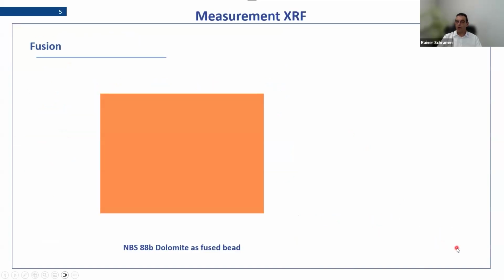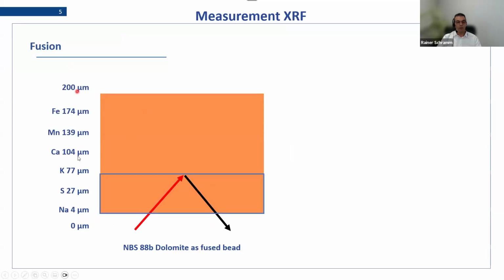But let's think about, we have a glass bead. And the glass bead was made from a dolomite, with a dilution ratio 1 to 8. So 1 part sample, 8 parts flux. And then the main question is, where is our information coming from in the bead? And for this, I just mention here the penetration depth for different elements. And you see that with increasing atomic number, the penetration depth is going up. And for example, for potassium, we will have a penetration of something around 80 micrometer in the bead.